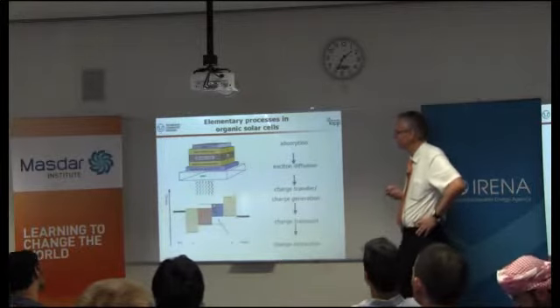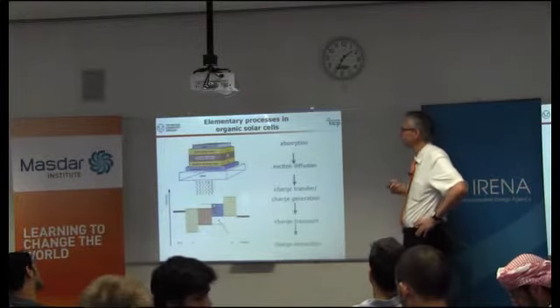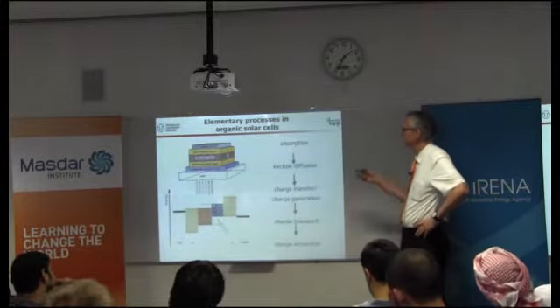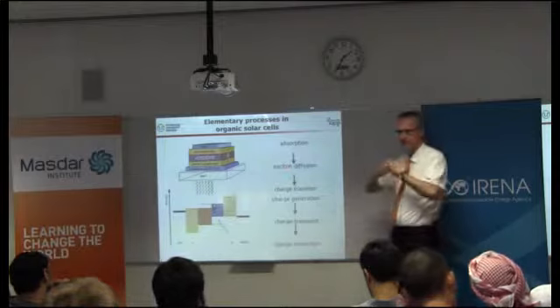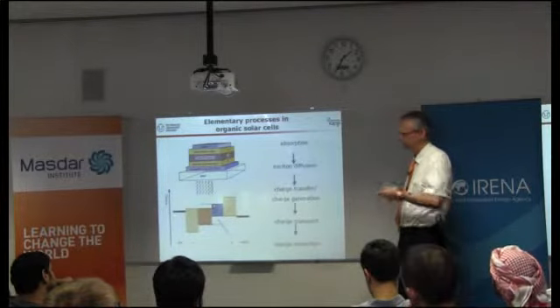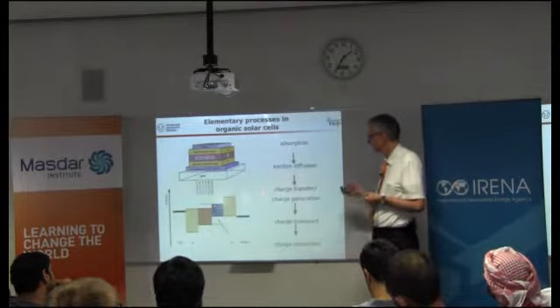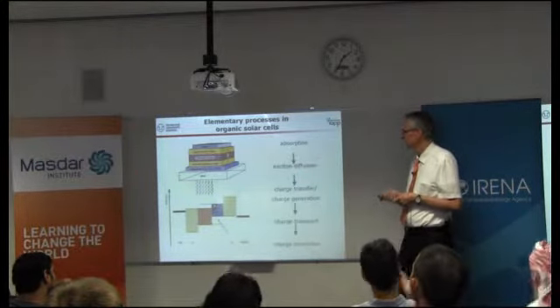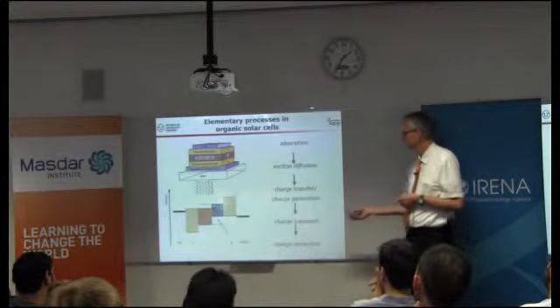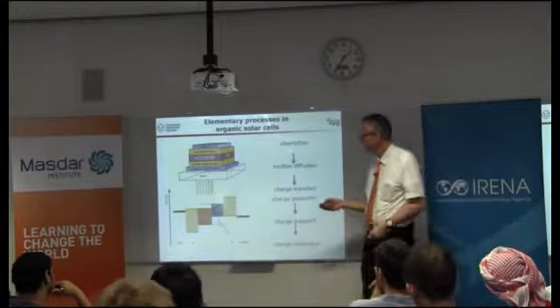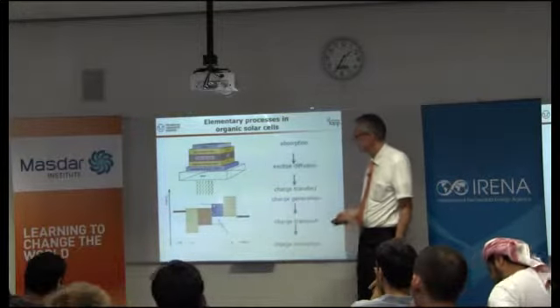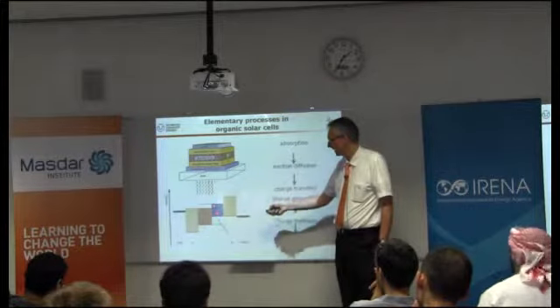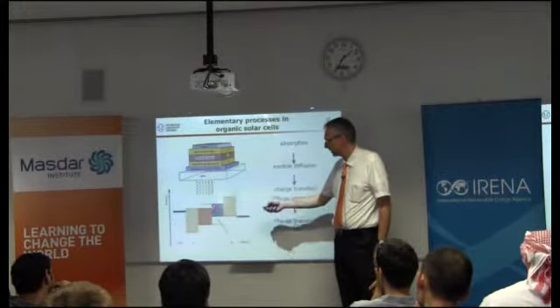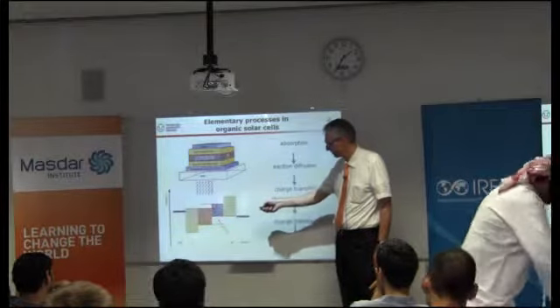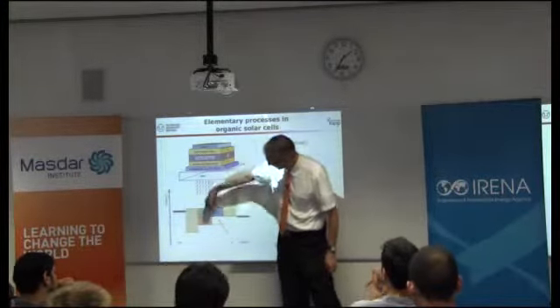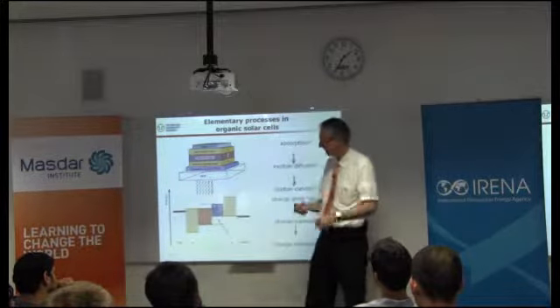Now, if you look at an organic solar cell, it's actually a somewhat more complicated device than a silicon solar cell. The main reason is when you have the absorption process, you generate excitons, bound electron hole pairs. And in silicon, they separate immediately, but in organics, it is not easy to separate them. So first you transport an exciton, then you separate it, and then you transport charges and extract them. And the way to separate this, I'll come back to that in a later slide, is that the exciton, the bound electron hole pair, has to travel to a boundary between two materials. And there's an energy step at the boundary so that the electron will fall down and the hole will stay here, and that separates the exciton.